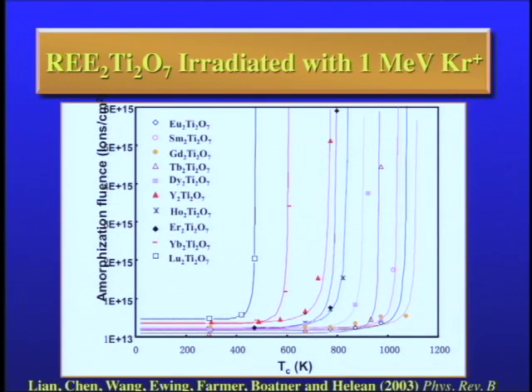Well, that was the B site. What about the A site cation? Well, if we synthesized all of the titanates with all of the rare earths in the A site, the surprise is this curve where it bends up, which we refer to as the critical temperature, covers a range of 400 to 1100 Kelvin.